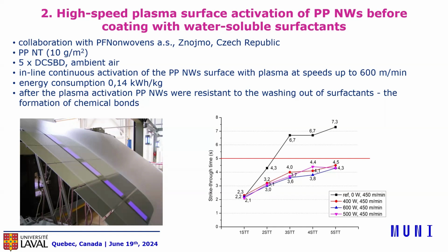Only this part was used for the testing. This strip of textile with a width of 8 centimeters was activated by plasma. Subsequently, it went to the kiss roll, where surfactants were put on the surface and dried. We did several tests, but again, I will talk about strike-through time. As you can see, here is the dependence of strike-through time on the number of washes of these samples. It means that we had one sample and we periodically measured the strike-through time on the same sample. For the black line, which corresponds to the reference sample, you can see that after the second wash or